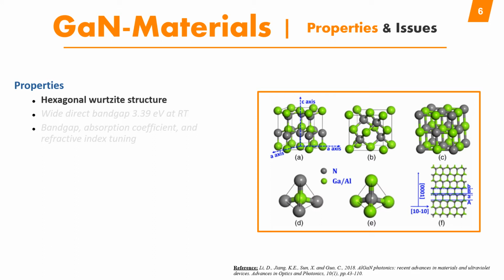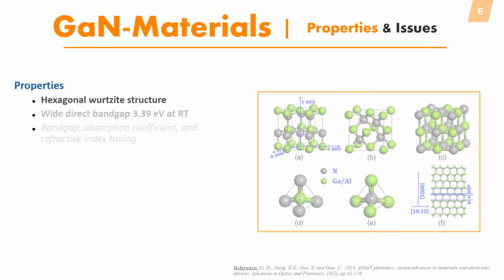For the layered structure of gallium nitride materials, we can see that they are arranged in the AB configuration along this 0001 direction, as we see here in this figure, where AB is gallium nitride, then on top the next layer will be another gallium nitride, ABAB, and so on. This is the layer structure in this direction. So these materials exist in the hexagonal wurtzite structure, which is the most stable crystallographic structure for these materials.